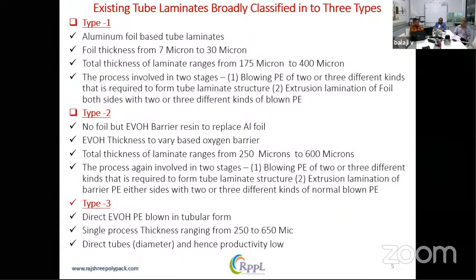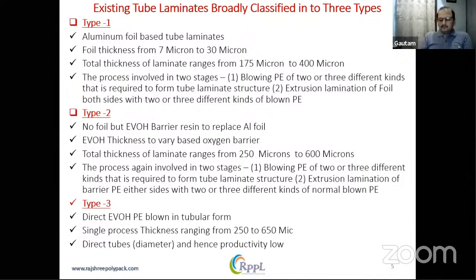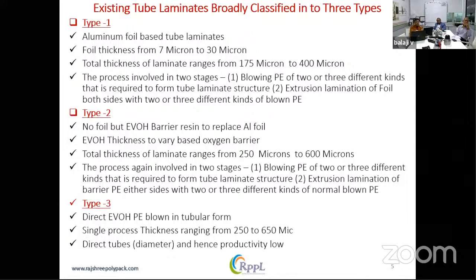I want to cover a very small point before we begin on what we want to do. There are three types of tube laminates. One is alfoil tube laminates. Foil thickness ranging from 7 to 30 microns. Total thickness of the laminate ranging from 175 to 400 microns. The process involves two stages: blowing of PE of 2 or 3 different kinds that is required to form tube laminates, and extrusion lamination.